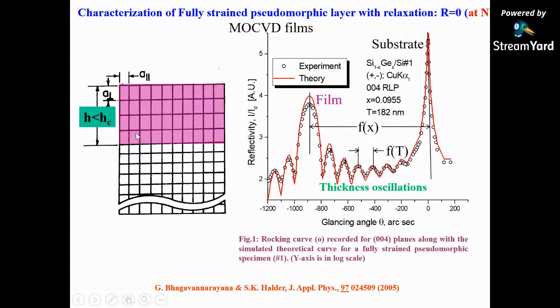But in doing so, there is an elasticity. If there is a compression here, there will be elongation in this direction. So by measuring this A perpendicular and A parallel by X-ray methods, you can measure the composition or the thickness in nanometers of any structure, like a silicon germanium layer on silicon. The substrate peak contains an additional film peak, and this distance is a function of the composition of germanium here, and the fringe width of this beautiful thickness oscillation is a function of the thickness. By using the semi-kinematical method, we can measure this composition and thickness very accurately.